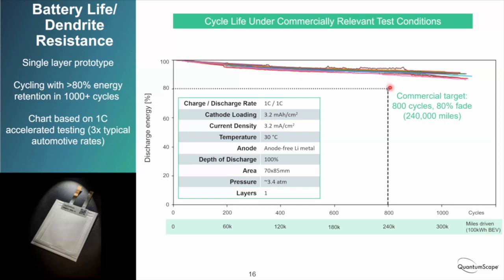Why 800 cycles? If you have a long range electric car of say 300 miles, and each cycle is a 300 mile range, then 800 cycles give you 240,000 miles. That's pretty considerable to 80% fade. And so this is showing batches of our cell performance here going out to over 1,000 cycles, cycling quite well under conditions that are listed in this table here. So we're also trying to be transparent about the test conditions for every test. And so we'll give you the test conditions here.